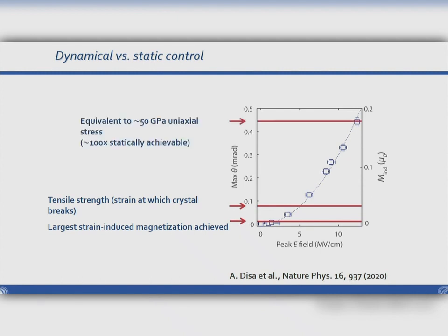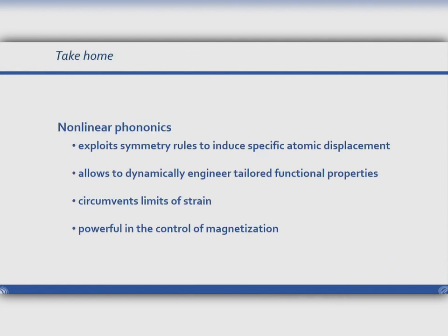If you really wanted to achieve that number, you would have to apply 50 gigapascal of uniaxial strain, which is a lot more than you can really do. And what we also calculated is that if we would be able experimentally to turn up further our excitation fields, we could maybe even go a factor of 2 higher in magnetization induced in this material.